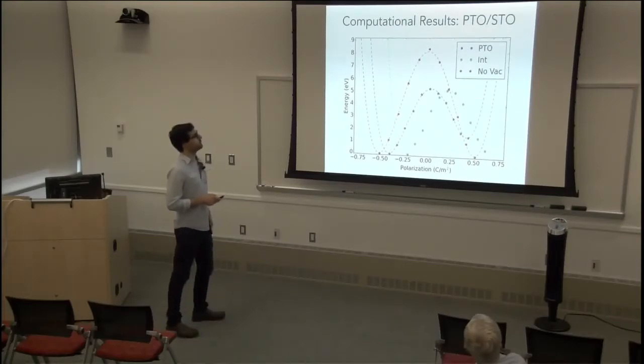Now we do this calculation where we simulate the system, relax it, calculate the energies, and go through the process of calculating the polarization, which is not trivial. First we end up with the pristine situation, which is the no vacancy case, and as you see, you get a symmetric double wall. Now we introduce the divacancy either in the lead titanate or the interface.